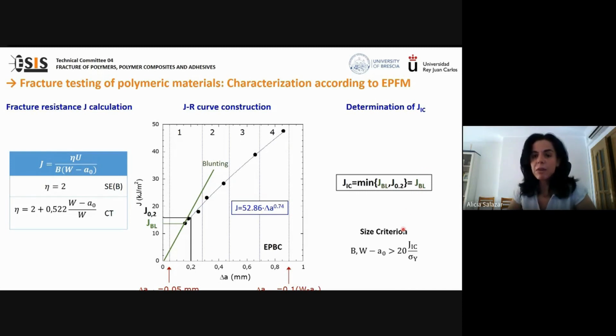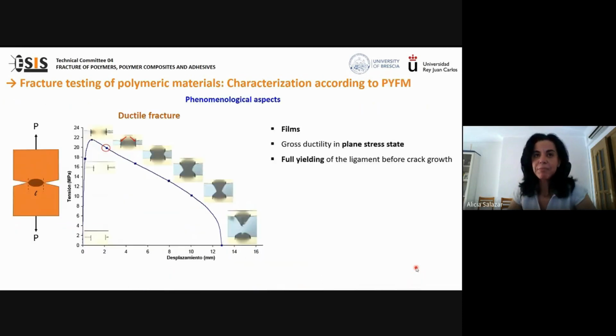To guarantee plane strain values, the following size criteria must be fulfilled. And finally, values of the energy at crack growth initiation of a ductile polymer such as an ethylene propylene block polymer can range between 10 and 20 kilojoules per square meter.